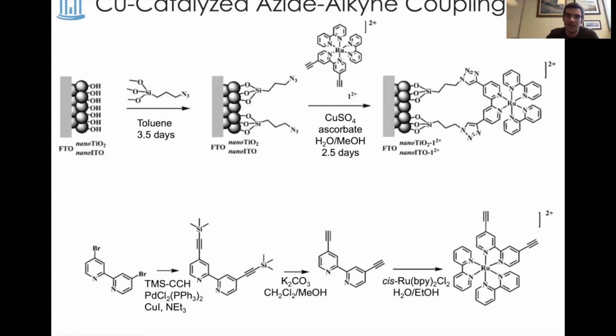or they wouldn't be compatible with the catalyst. And so the approach that was taken was to instead functionalize the surface with an azide group. So prepare a relatively simple azide-containing silane that could be rapidly synthesized and utilized before it hydrolyzes, and form a functionalized surface where you have strong anchoring groups in the form of these silanes, and then a new functional group in the form of the azide. And then a catalyst was prepared that has two alkynes, and you can see where this is going towards a click reaction where copper catalyzed cycloaddition was carried out to form these triazoles.